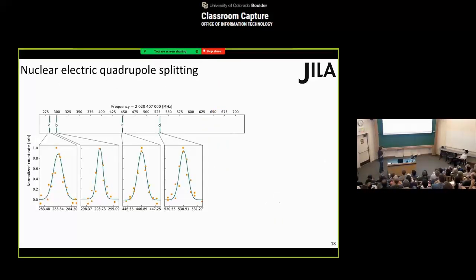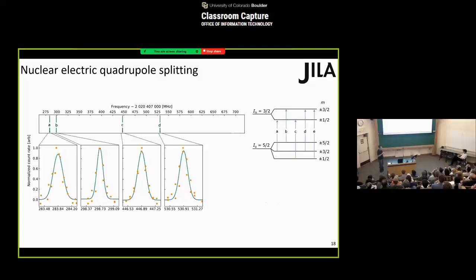We actually performed this absolute frequency determination for 4 of these dominant lines, and their frequencies and line shapes are shown here. The reason we have a couple of different transitions is because we have a quadrupole interaction, an electric quadrupole interaction between the nucleus and the crystal. So we expect to see actually 5 splittings. And the line E is missing here because it's a weaker transition due to the smaller CG coefficient, so its intensity is expected to be about a factor of 10 lower.